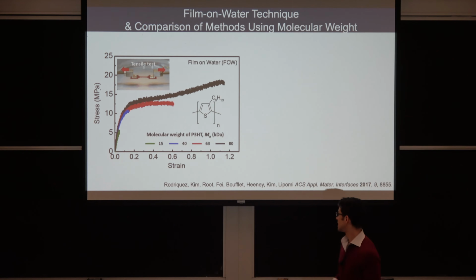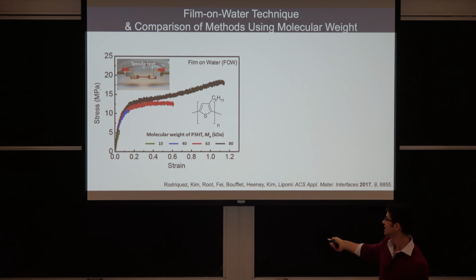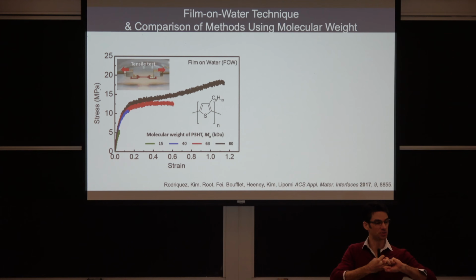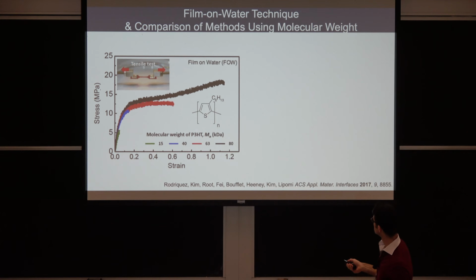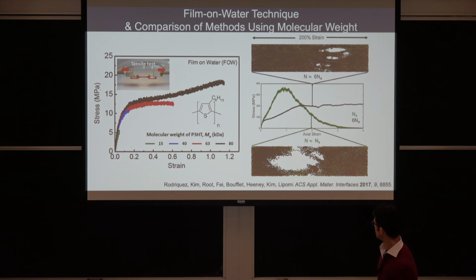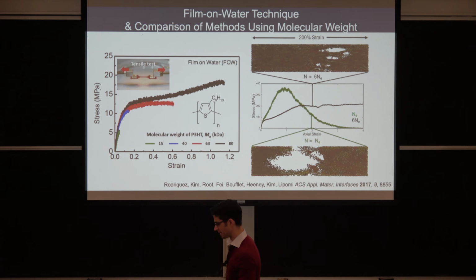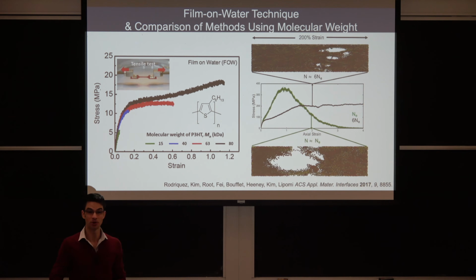So this is a tensile test of this material. This is poly-3-hexylthiophene, and we've plotted the stress-strain curves as a function of molecular weight. Now, as you increase the molecular weight, you're increasing the number of entanglements that you can have between chains, so that's where they literally entangle. And as a result, you increase the toughness, so the energy density prior to fracture. These are the results of a molecular dynamics simulation that more or less tell you the same thing. That is, you increase the molecular weight from 15 to 80 kilograms per mole, you have a factor of about 6 more